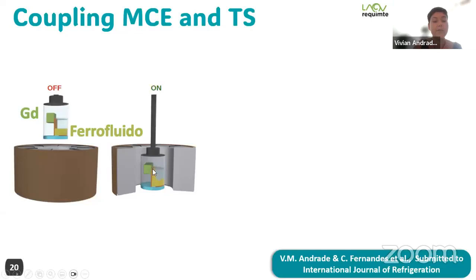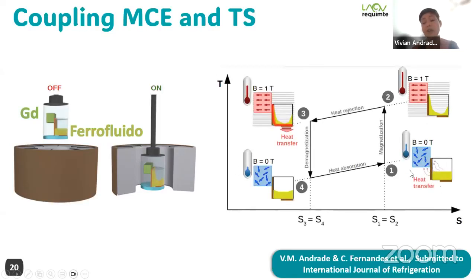We put the gadolinium, so magnetic caloric material, in height high enough so it will not touch the fluid when it's outside the field, and it will operate in a cycle where, outside the field, heat convection is the only means of heat transfer. When the magnetic field is applied, the magnetic caloric material increases its temperature, and the fluid gets in contact with it, transferring heat to the heat sink, and when the field is removed again, the cycle begins again.